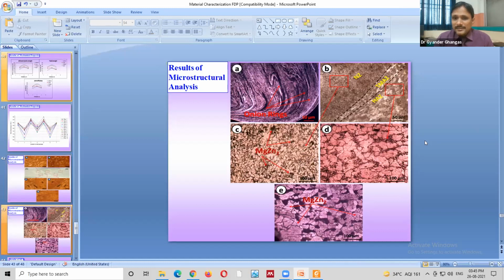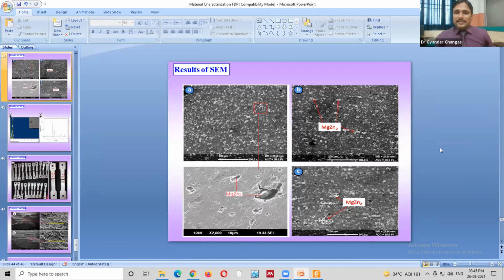Another specimen is also characterized by microstructure, and here, from the study of the literature, it is written that these precipitates are MgZn2, but this is not confirmed. So we went for further magnification with the help of SEM to confirm the distribution of the precipitates. These are the precipitates distributed over the nugget zone, and there is a difference between the distributions. Here we can see some clusters. This proper distribution and clustering of these precipitates gives the difference between the properties of two different specimens.